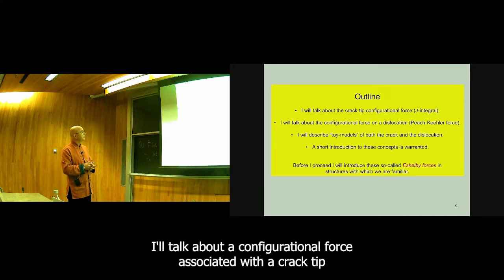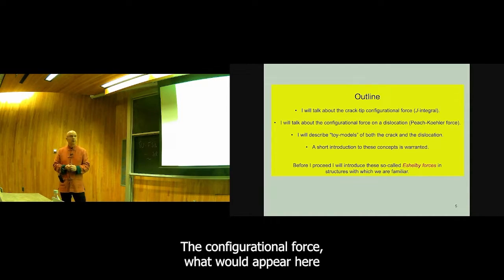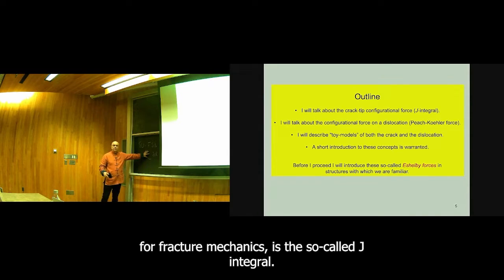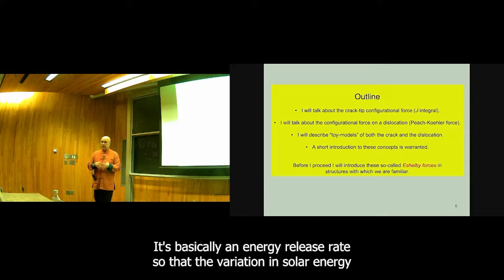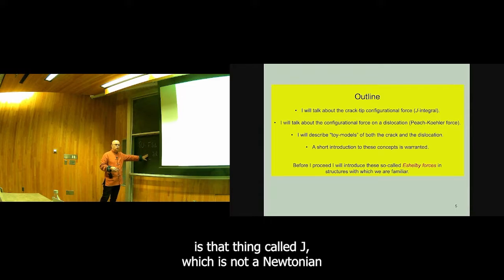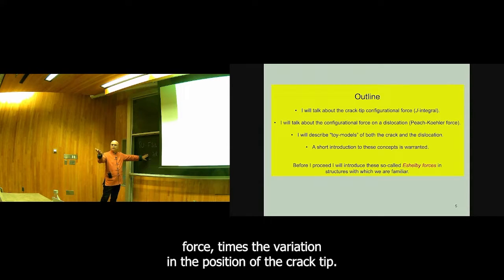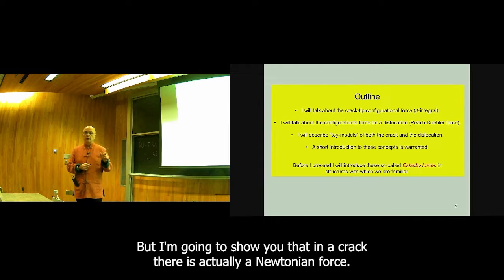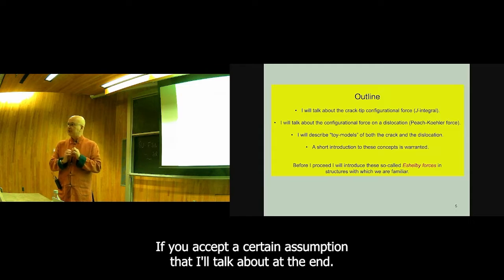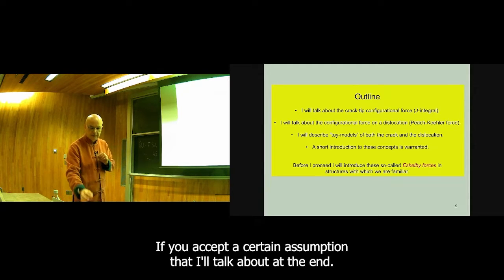I'll talk about a configurational force associated with a crack tip in an elastic body. The configurational force, what would appear here for fracture mechanics, is the so-called J integral. It's basically an energy release rate, so that the variation in some energy is that thing called J, which is not a Newtonian force, times the variation in the position of the crack tip. But I'm going to show you that in a crack, there is actually a Newtonian force, if you accept a certain assumption that I'll talk about at the end.